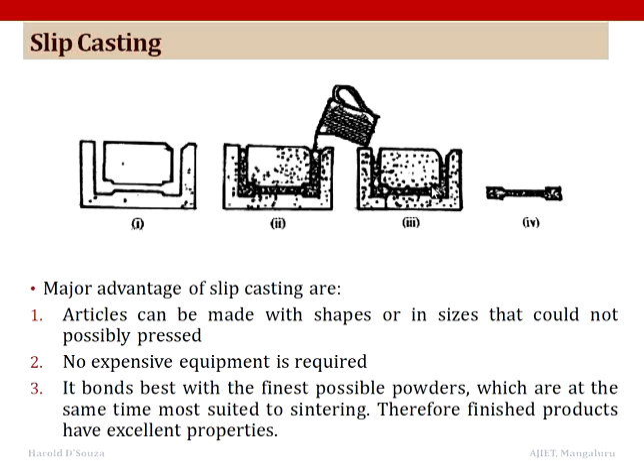For successful slip casting, the settling time for the slip in the mold is critical, as is the time for letting the slip cast shape dry in the air at room temperature prior to the further drying and firing. Now the density of slip casting is considerably higher than the tap density of the powder from which the casting is made. Now since the suspension in the slip decreases the friction between the powder particles, it is possible to make complex shapes by using multi-part molds. Hollow parts can also be readily produced.